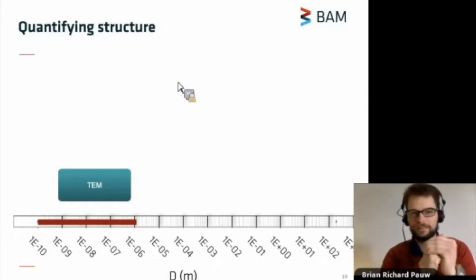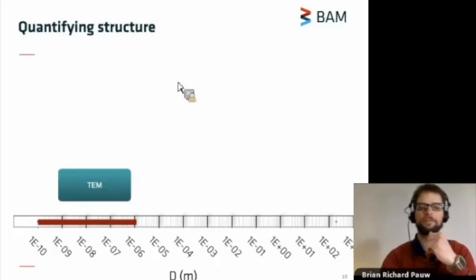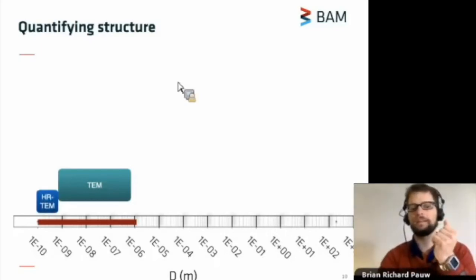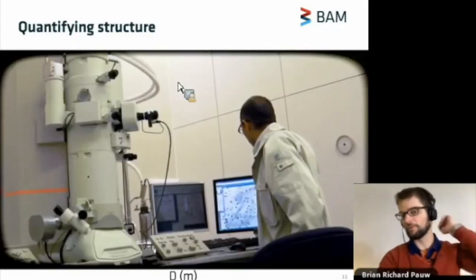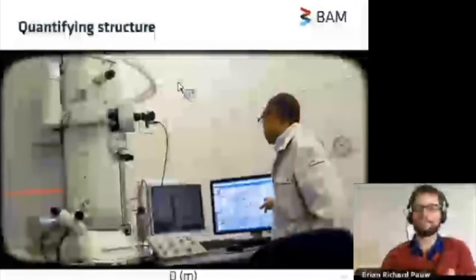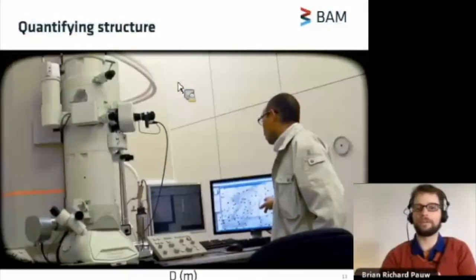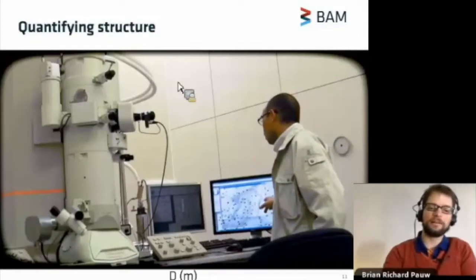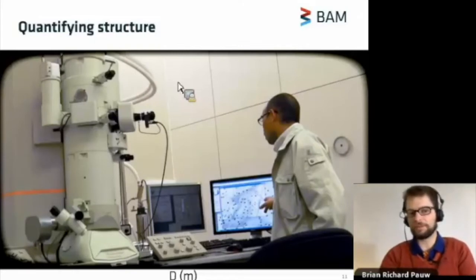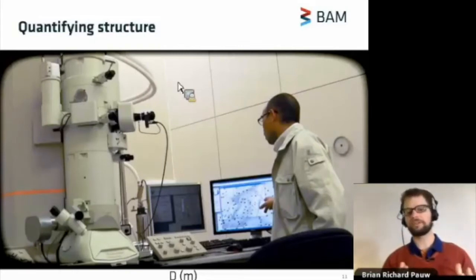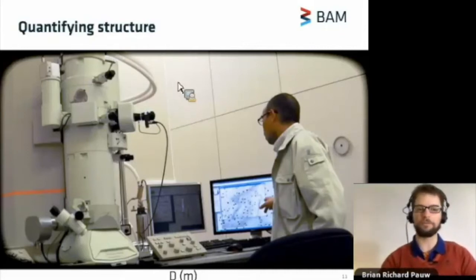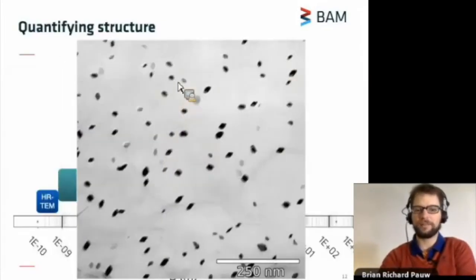And this is an absolutely essential technique. This technique and its high resolution variant in the hands of an experienced electron microscopist will allow you to get an insight into the real space structure of your material. Now, I emphasize that you need an experienced microscopist for this because, besides an image of the structure that you're seeing, you're also seeing a lot of artifacts either from sample preparation or from the microscope itself. And this microscopist will be able to tell you which parts come from the microscope, which parts are actually from your sample. But when it comes to quantifying this structure, things get a little bit harder.